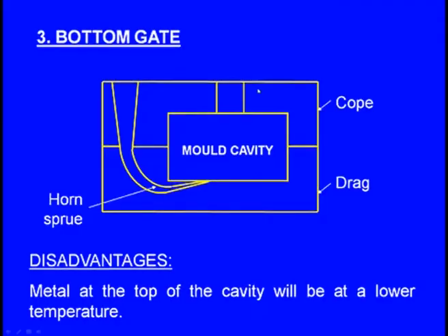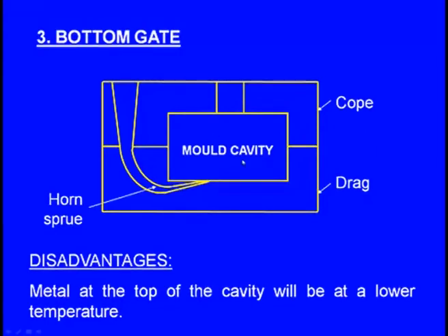Now, what is the principle in the solidification? The riser should be the one which has to solidify at the end. Then only it can supply the molten metal to the casting which is undergoing the shrinkage. Now, in this case, what will happen? The upper portion of the liquid metal will be at a lower temperature. Naturally, even the liquid metal in the riser will be at a lower temperature, whereas the liquid metal at the